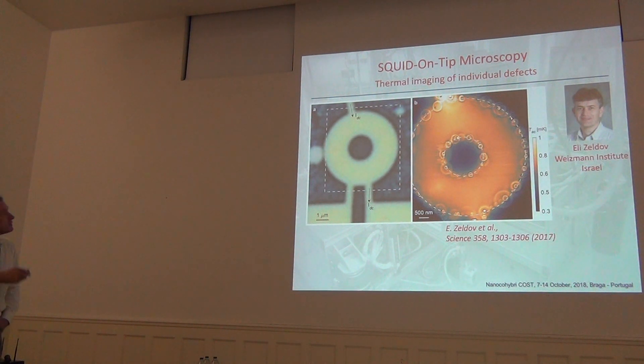And last but not least, now, by measuring the Josephson critical current of your device instead of measuring coil, you can get immediately a temperature picture of your situation and you see that this permalloy heats up because it's resistive. It's much more resistant than copper. So you get also thermal imaging. And very recently they published this very nice paper in which they created a disk of graphene. This disk was made of encapsulated graphene on boron nitride, and the edges were cut by lithography, and this is a temperature map. They inject the current here. Of course you have a very high temperature here, you see it as bright spots, but what is very nice is that you can see some circles around some single points and these single points are individual atoms that scatter electrons and produce dissipation. So you can get images of individual dissipators of electronic waves.